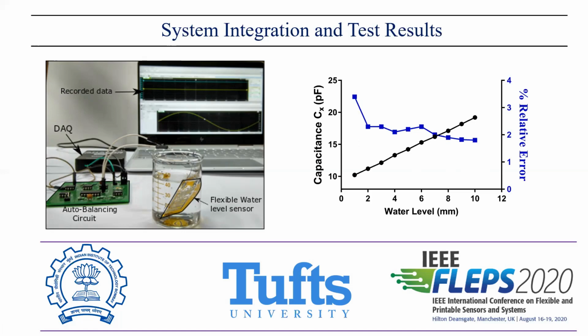So the output shown here represents the change in the capacitance for different water levels. Here we can see we obtained a very linear changing output. We changed the water level from 1 mm to 10 mm, and we observed the change in capacitance from almost 10 picofarad to 20 picofarad, which shows that the variation in the capacitance is around 1 picofarad for a 1 mm change in water level. And we can also see that the relative error of the circuit is quite low.